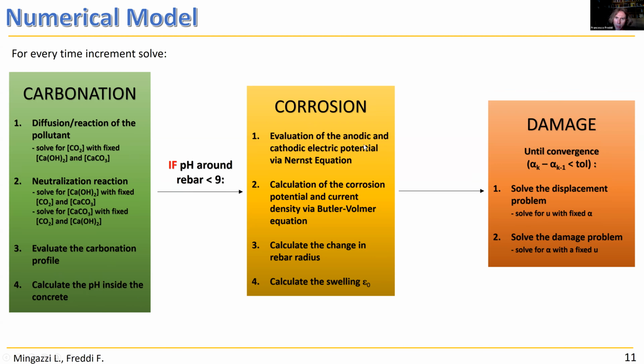So I calculate the anodic and cathodic potential via the Nernst equation, calculate the corrosion potential, and the current density via the Butler-Volmer equation. After that, I calculate the swelling, so the changing radius of the bar and the swelling deformation. After that, I solve in an iterative way, via an alternate minimization algorithm, the mechanical problem to determine the crack pattern within the solid.